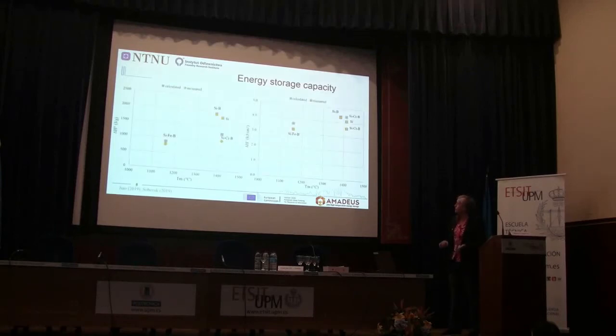So if we look at our materials, so this is the Joule per gram. So here we have the silicon, silicon boron, silicon chromium boron, and silicon iron boron. And these are both calculated based on thermodynamic data and measured as well. So we see they are in quite good agreement, a bit off with the chromium, but this is work also in progress. Because again, if you are going to measure the enthalpies, the sample can't react with anything, right? Because then you will get an offset. So, however, here is per gram, per mass unit.